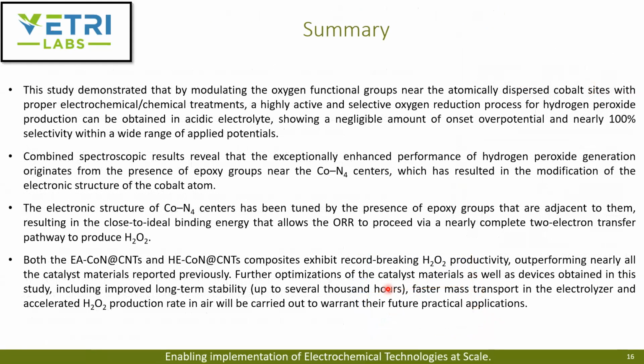In summary, they demonstrated that by modulating the oxygen functional groups near the atomically dispersed cobalt sites with proper electrochemical and chemical treatments, you can obtain a highly active and selective oxygen reduction process for peroxide production in acidic electrolyte, showing a negligible onset overpotential and nearly 100% selectivity over the full potential range. They combined spectroscopy results to reveal that this exceptionally enhanced performance of peroxide generation indeed originates from the presence of epoxy groups near the CoN4 centers, which modified the electronic structure of the cobalt atom.